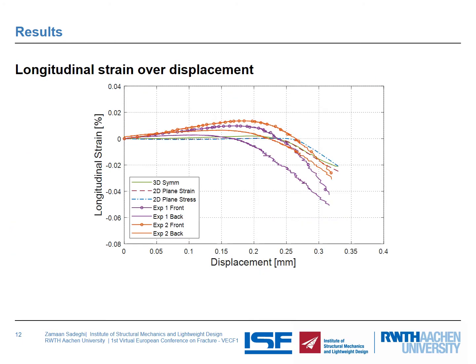The longitudinal strain over displacement for the single lap joint tested and also FE analysis is shown in this slide. The comparison of FE and experimental showed interesting results. As you can see, the FE results always show much lower values of strain compared with experiments. This is surprising since the previous FE results showed a good agreement for predicting low displacement curves. Apart from that, you can see that even for experimental results, one cannot see a general good agreement.